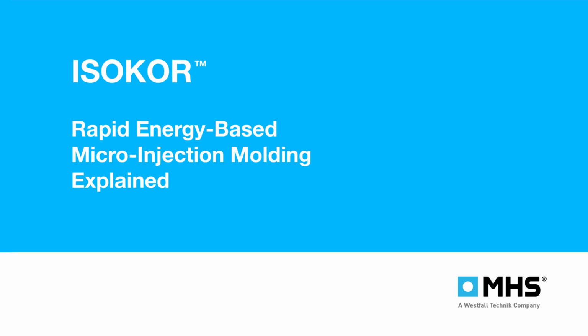Precisely. ISOKOR is radically different because of that step 1 I mentioned, constant pre-compression. The pressure in the MDU never, ever drops to zero. Oh, I see. We are starting the cycle from a higher baseline melt density, stepping it up to a plateau, and ending with a higher melt density in the cavity. Because the molecules aren't being subjected to massive violent pressure swings, the final micropart has significantly less internal stress, far less warpage, and vastly superior cavity replication. That solves the pressure pulsing problem beautifully.